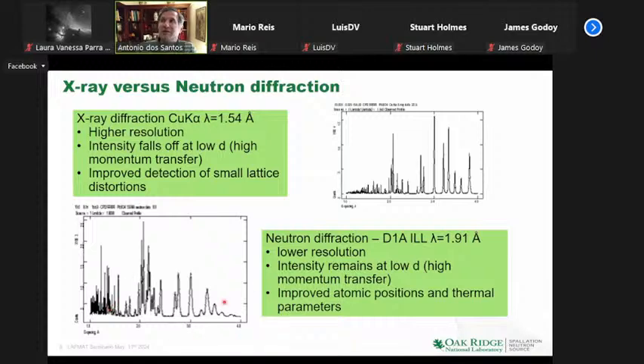The other thing you can see is that the peak intensities are a little messed up. They're not the same. And this is because of what I mentioned. Each peak is weighted, in this case, by the neutron cross-section. Here, each peak is weighted by the X-ray scattering length. So you can see here, for instance, that if it's a lead oxide, you will barely see any oxygen. If you have this same lattice with just lead, you'd account for probably 80 or 90% of all this intensity. While here, everything is much more evened out. So you can get your oxygen positions much better, not just because of this extended Q, but also because more of the intensity on each peak comes from the oxygen.